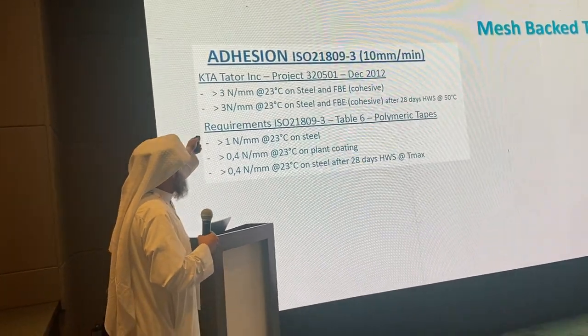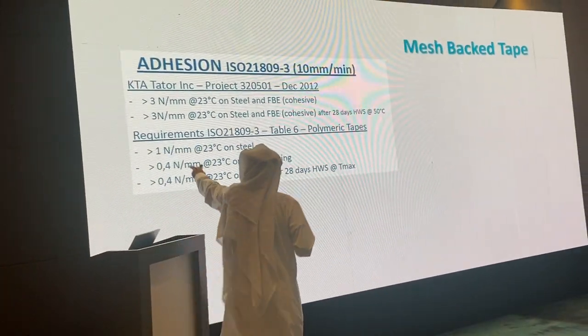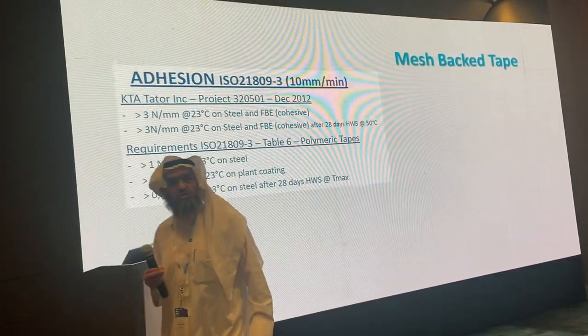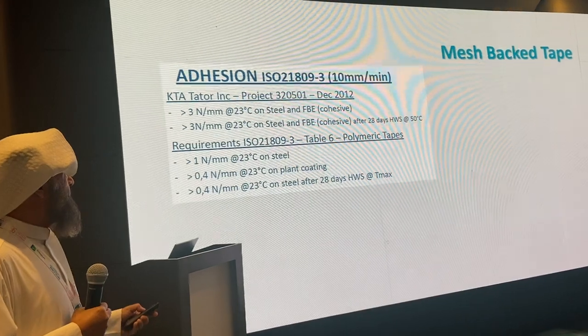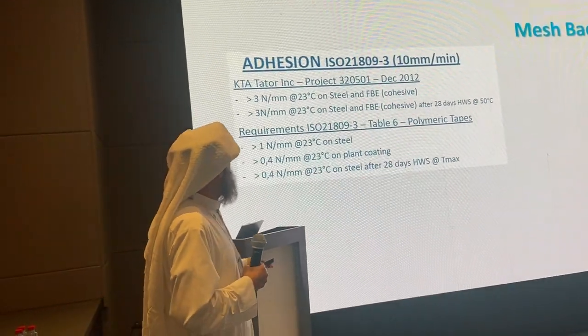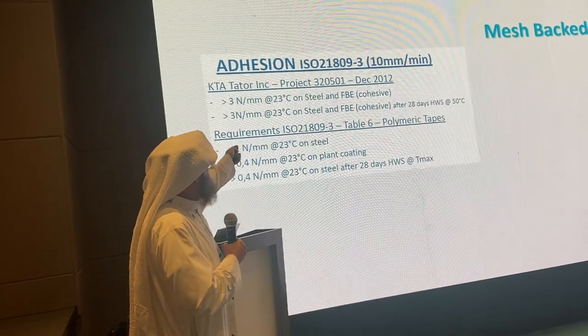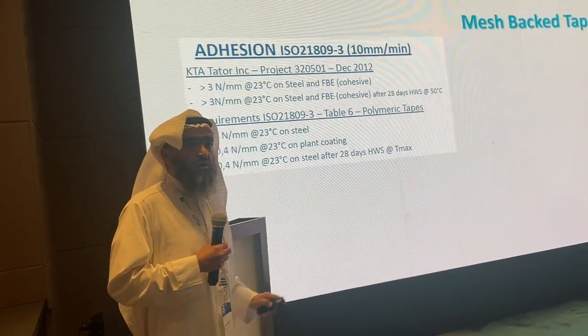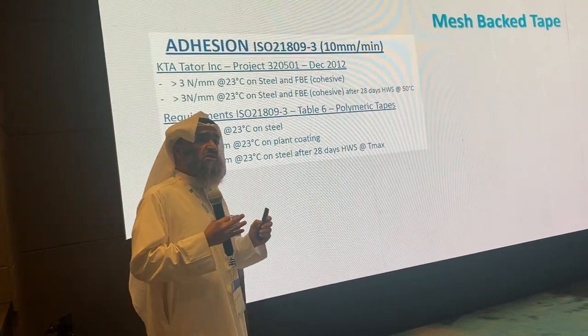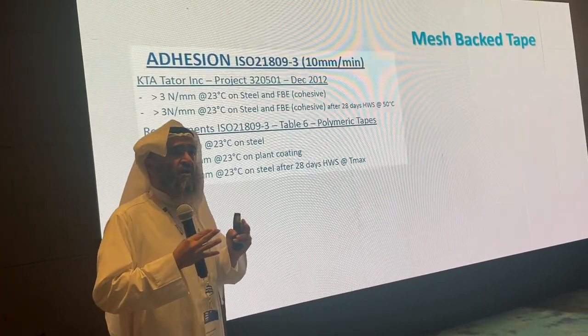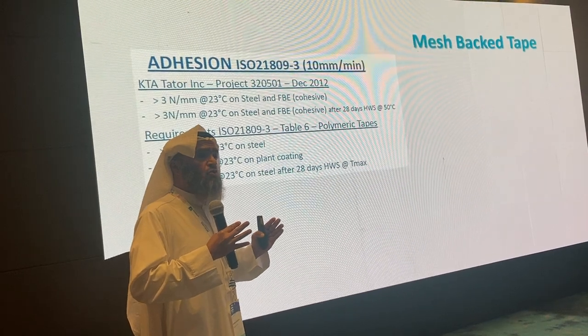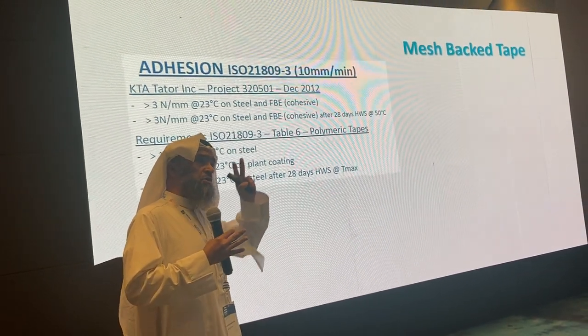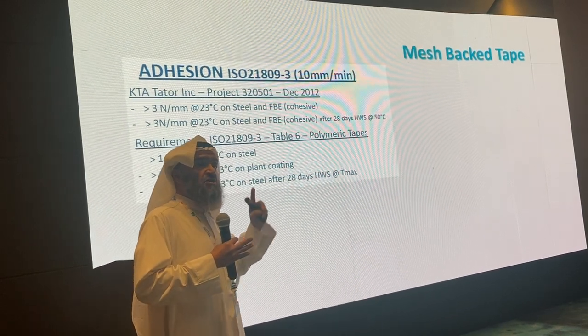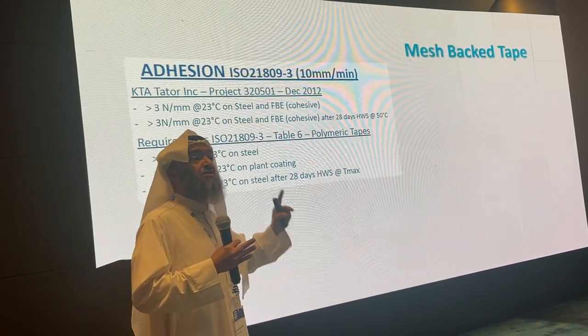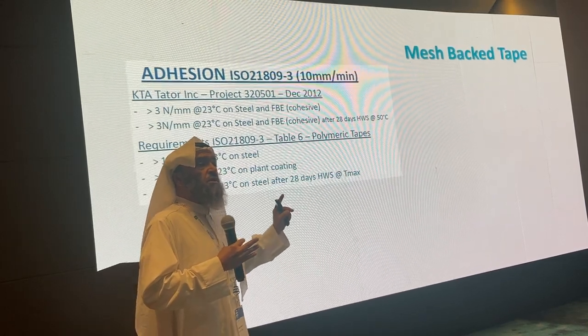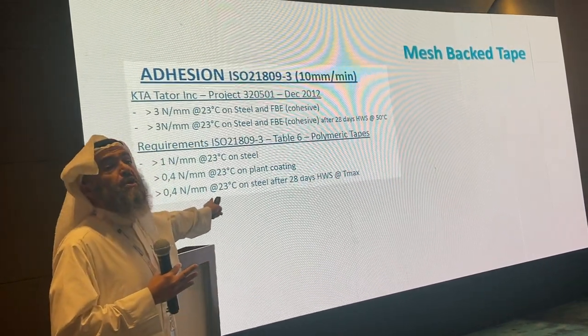What does 3 Newton per millimeter mean? It means 3 times the European standard, which asks for 1 Newton per millimeter on steel at 23 degrees. It also gives 3 Newton per millimeter on FBE, which you cannot get from other coatings. So, to conclude, to have non-shielding and to prevent your pipeline from stress corrosion cracking, you need 2 factors. First, CP, non-shielding. Second, very strong adhesion to prevent cathodic disbondment. And you get it only from this mesh-backed tape.